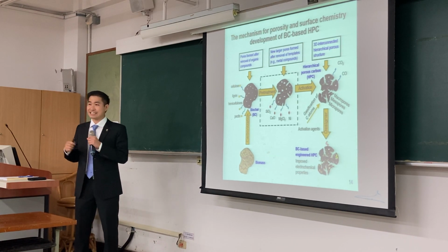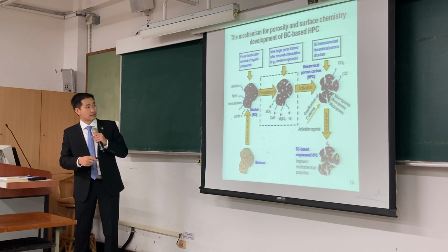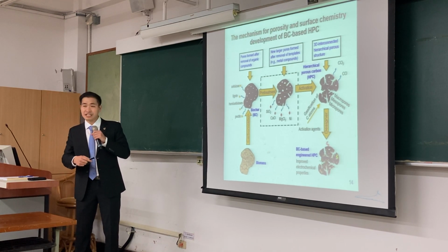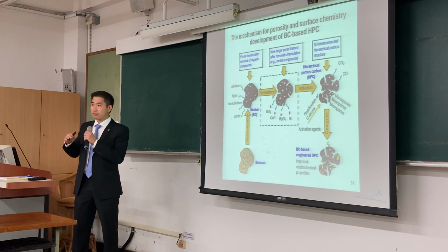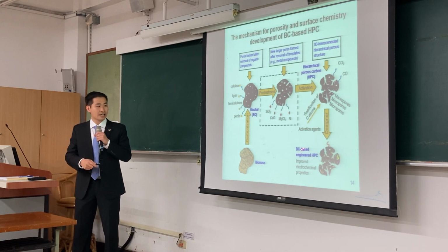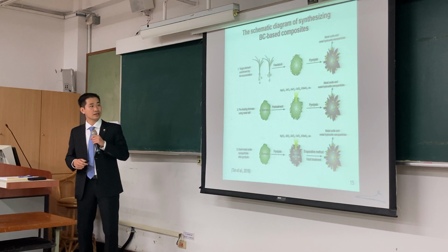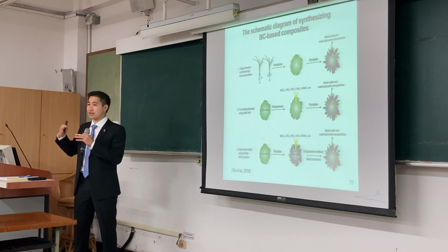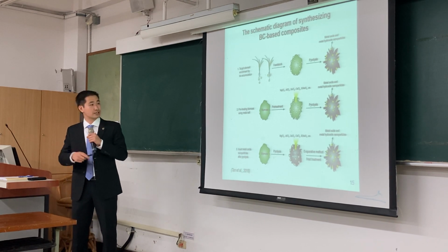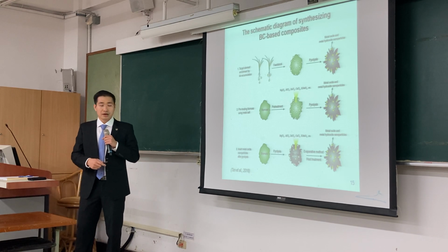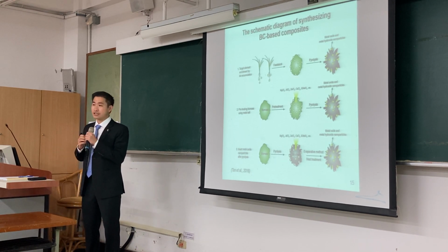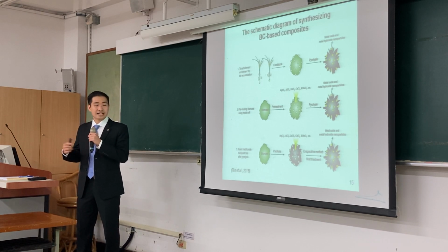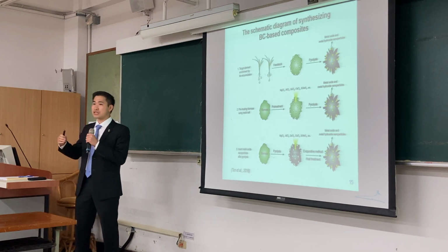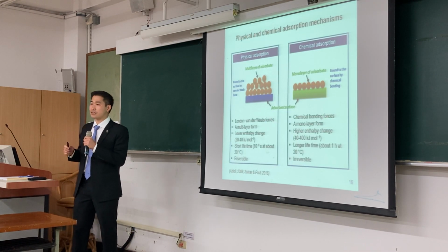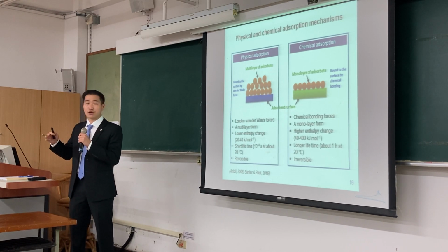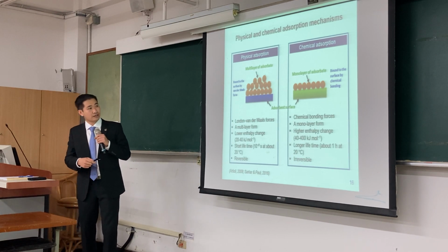The development of porosity in HPC material can undergo carbonization, pre-treatment, and activation processes. Moreover, the surface chemistry of HPC can be enhanced by a doping step. On the other hand, biochar composite materials have many attractive properties for removing pollutants from water. Metal oxide and metal hydroxide modified biochar is a common composite that can be prepared by coating metal oxide on the biochar surface. To understand the adsorption mechanism, the theory of adsorption was summarized in this slide.